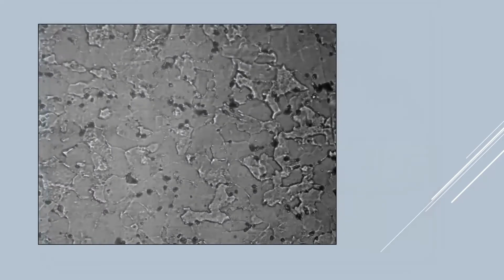Another thing that's an artifact, because we're going to go over a few of these artifacts, is that all these little black particles that you see on this microstructure are refractory dust. They're abrasive. So I'm trying to polish something down to a mirror finish, and they're falling on the surface, and it's going to give me scratches all over the place. And there's nothing much you can do about that because these particles are suspended in air. So you can't put up a tarp or anything. That's one artifact that you can't prevent. The other one where I just didn't remove the scratches, that was my fault.